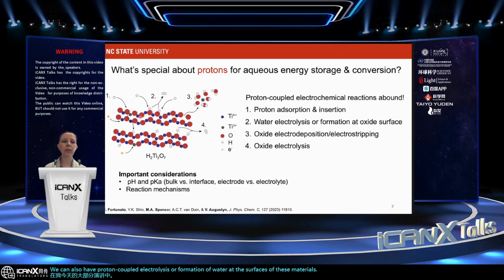So these surfaces of metal oxides are serving as catalytic sites for the subsequent reaction of molecules in the water-based electrolyte. You can also have proton-coupled electrodeposition, or in this case, what's illustrated here is stripping of the oxide. So where the proton will come in, and instead of inserting and remaining in the solid state structure, it actually drives the dissolution of the transition metal into the electrolyte.